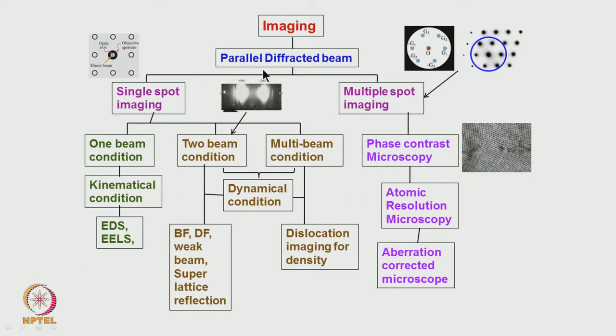And then the other case is that we get a symmetric diffraction pattern, and choose only two beams, the central beam and another beam, by tilting the sample. This condition is called the two beam condition. This is the condition which is used most of the time to get bright field, dark field or weak beam images, various types of images which are being formed. And specifically, if you want to find out the dislocation density, it is better to use a multi beam asymmetric condition and put an aperture around the central beam.